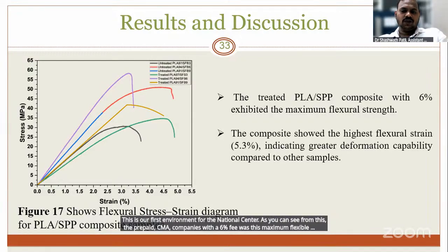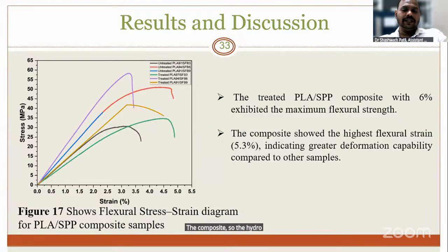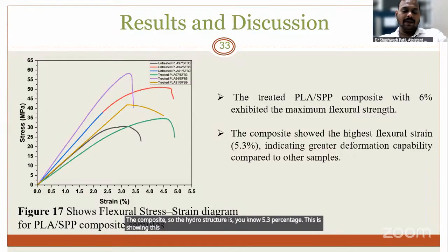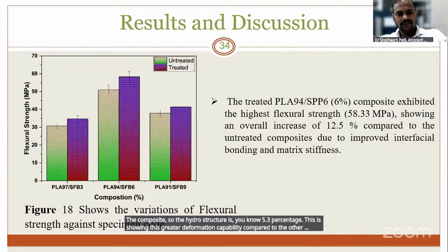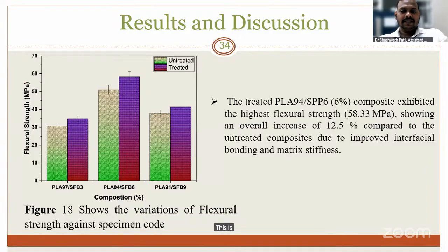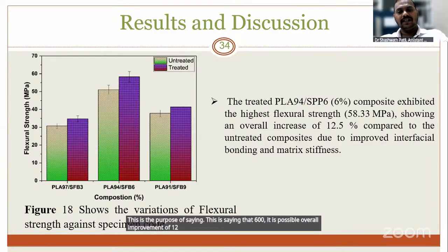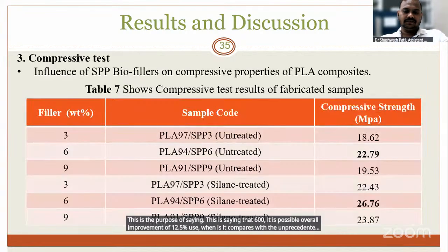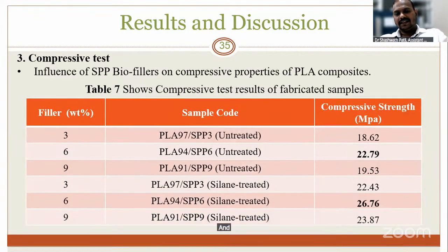The composites show the highest flexural strain of 5.3%. This shows a greater deformation capability compared to the other previous samples. This is the bar graph of change, showing that 6% filler gives an overall increment of 12.5% when compared with the untreated samples. And then these are some of the results of compression. Here also, as you can see, 6%.